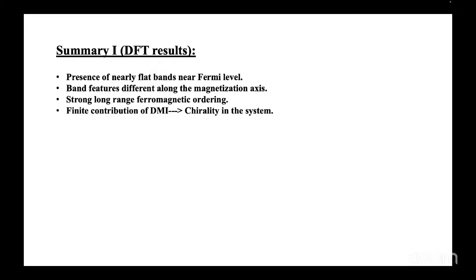What do you mean by strong ferromagnetic ordering? That is, we have a very high value of the ferromagnetic coupling for the first 4 nearest neighbor interactions. So you say that ferromagnetic couplings dominate. Yes. Then we also have some finite contribution coming from the DMI interactions, which points towards the presence of some kind of chirality in the system.